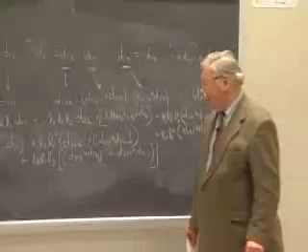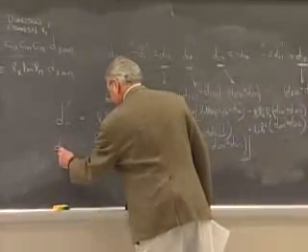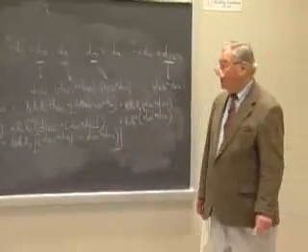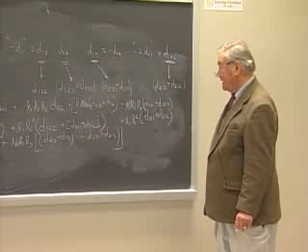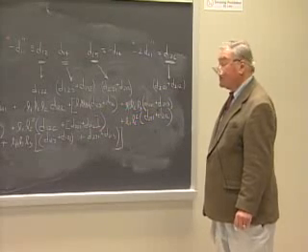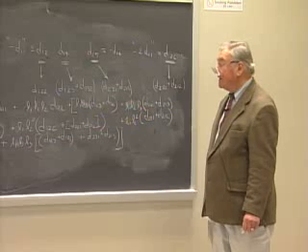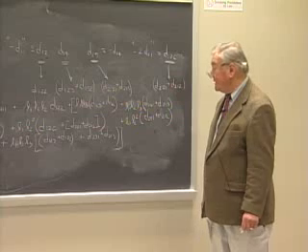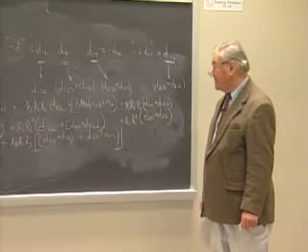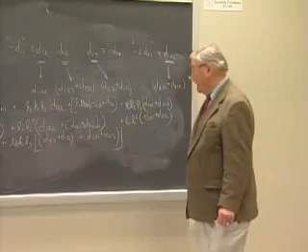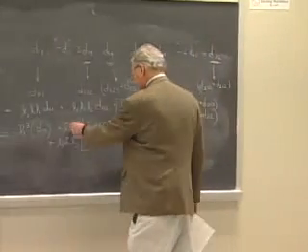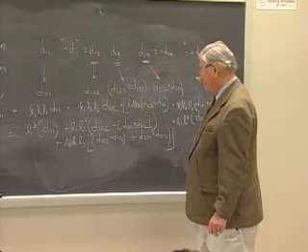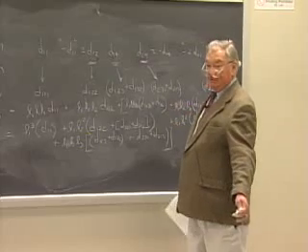Okay, that is how the longitudinal piezoelectric modulus will change as we change the direction of the normal to the plate that we have cut out of the crystal. So these are direction cosines relative to the crystallographic axes. L3 is the cosine of the angle between the normal to the plate and the threefold axis. L1 is the cosine of the angle between the normal to the plate and one of the twofold axes, and L2 is the direction cosine for the normal to the threefold axis and the twofold axis. Okay, so we've got it now in terms of tensor elements.